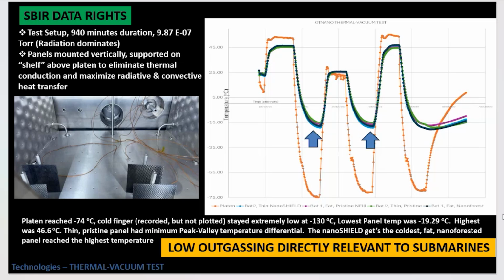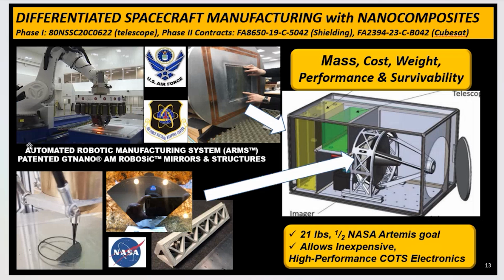So the quick question on the mirror, was the surface of that mirror your material as well, or were you scaffolding for a mirror surface? Oh no, this is 100% silicon carbide. The thing that I should point out is, compared to any 3D printed mirrors that you've seen by other players, they're all reaction bonded silicon carbide, which means that they printed a porous silicon carbide body, and then they melt infiltrated with silicon, and then they had to go back and polish it. With our process, we have 100% silicon carbide. Everything is made dense from the get-go.